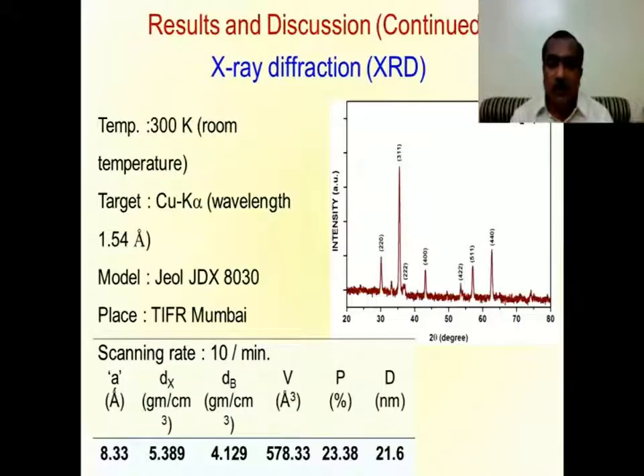This is the X-ray diffraction pattern of the cobalt ferrite. You will observe that there are different peaks located at different Bragg angles, and there is no impurity peak. All are clean X-ray peaks. The intense and broad nature of the XRD pattern indicates the nanoparticle nature. When you analyze the X-ray diffraction pattern by software, it is observed that the product so produced is of single phase.